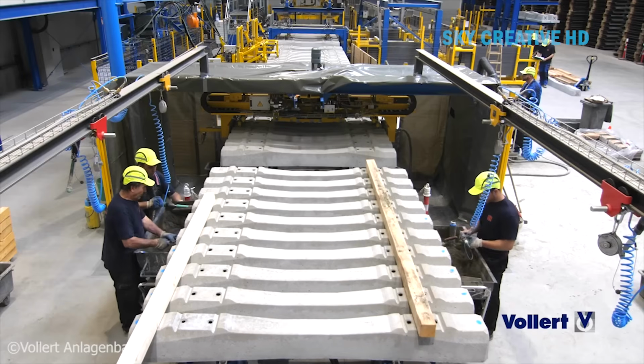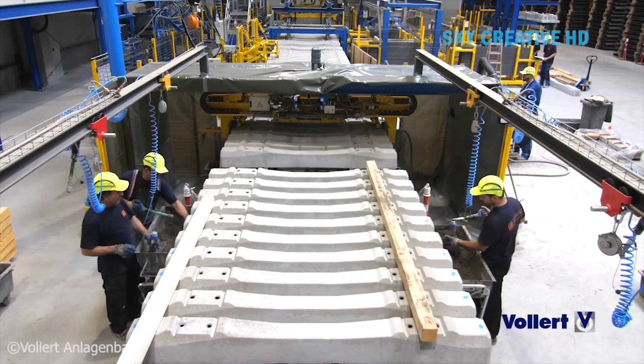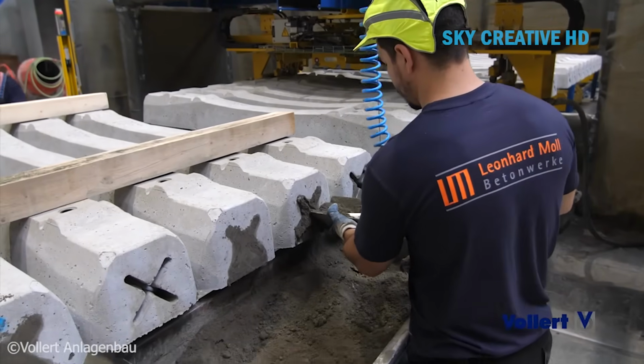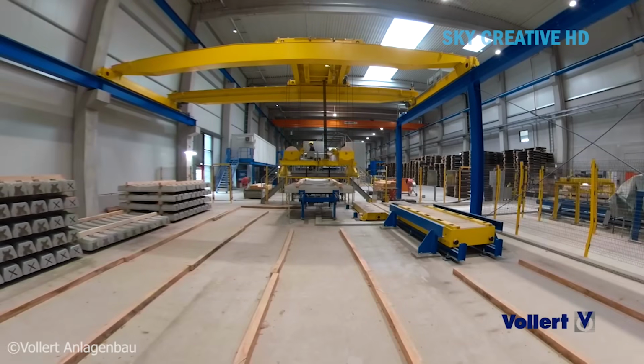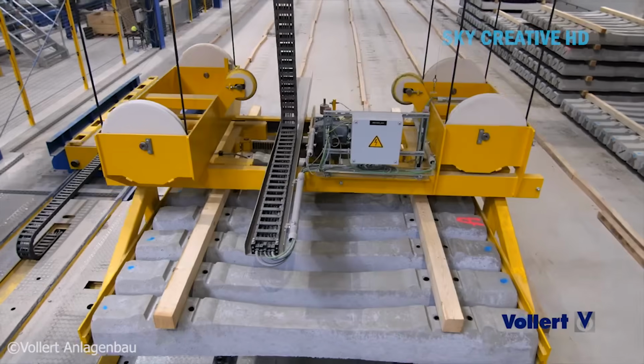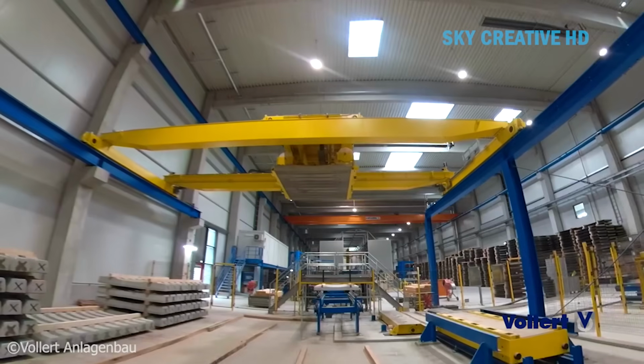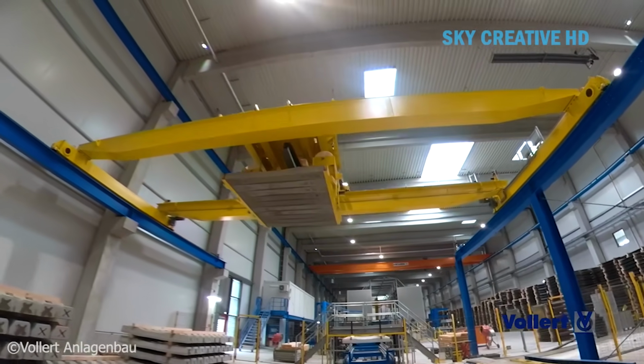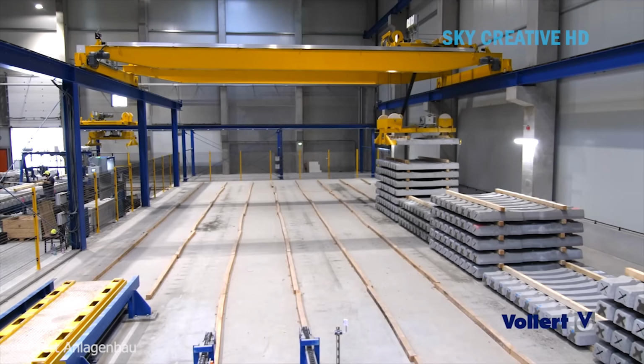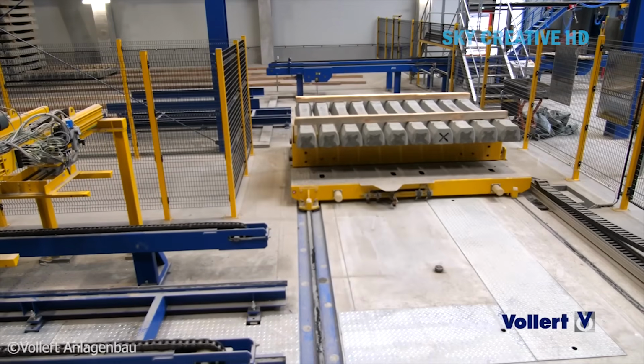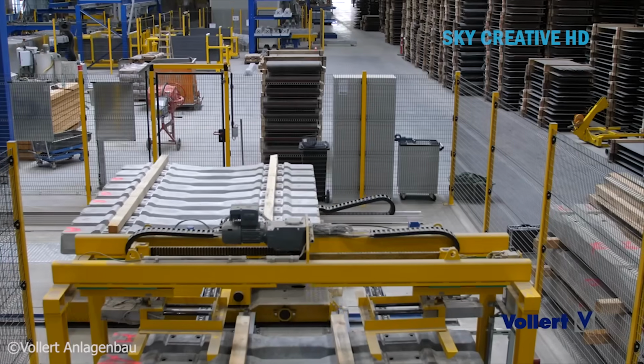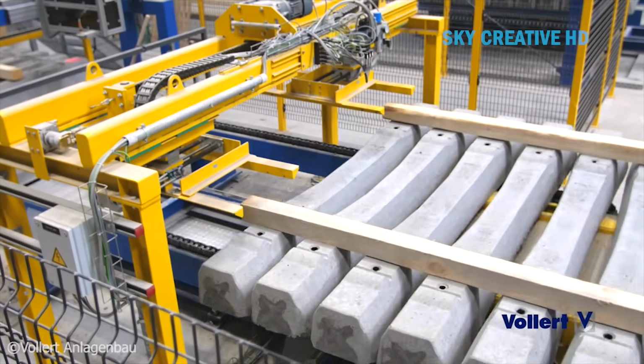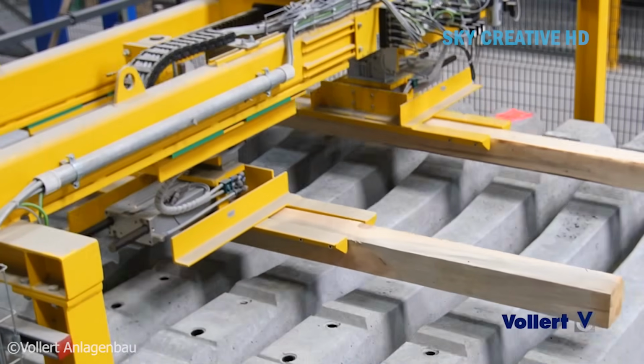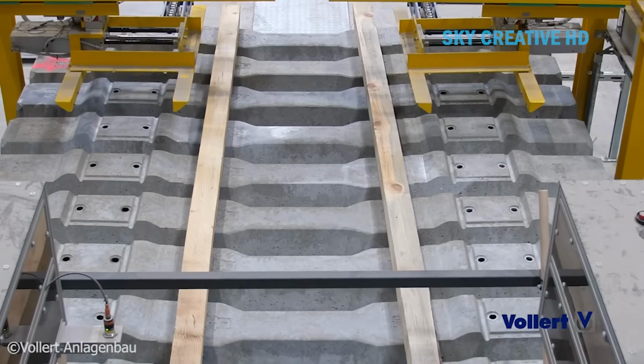Concrete samples from each batch undergo compression testing, and finished ties are subjected to load testing that simulates decades of service in just minutes. Some ties are tested to failure, and the forces required are truly impressive, often exceeding 100,000 pounds before cracking occurs. The final step involves aging. Yes, concrete actually gets stronger with time. These ties are stored in carefully controlled conditions for 28 days, during which the concrete continues to cure and strengthen. By the time they're ready for installation, each tie represents a perfect marriage of materials, science, and precision manufacturing.